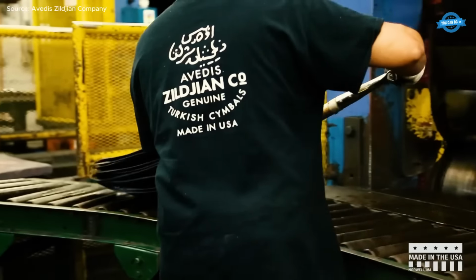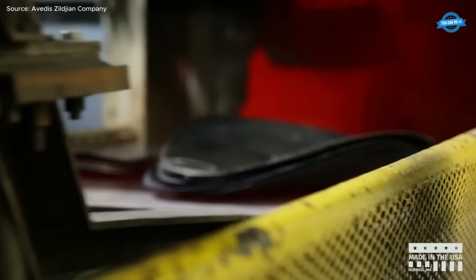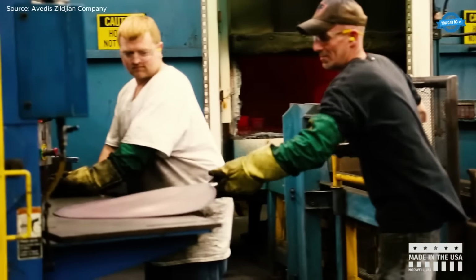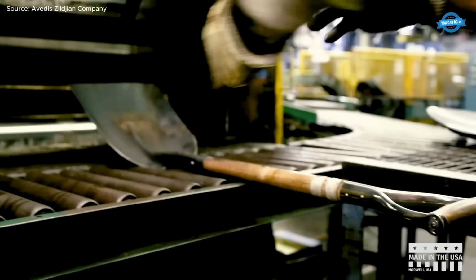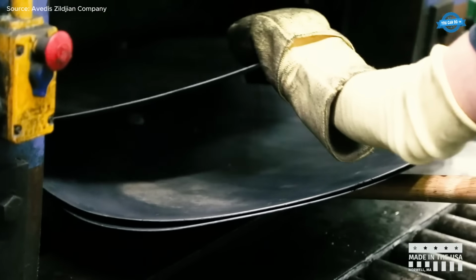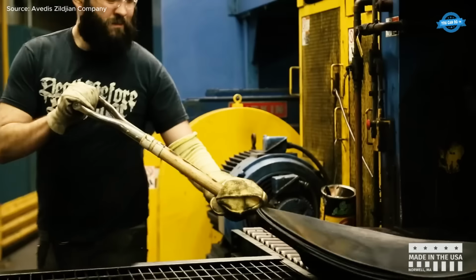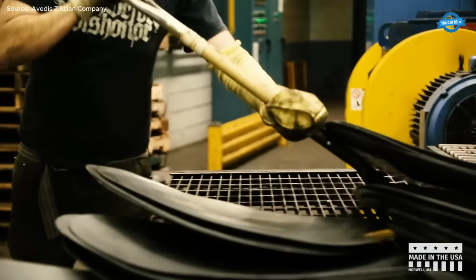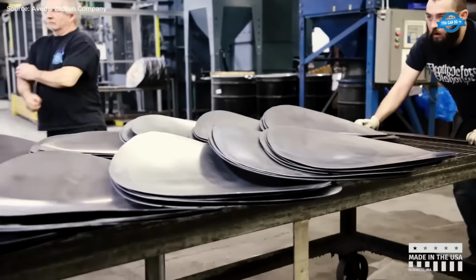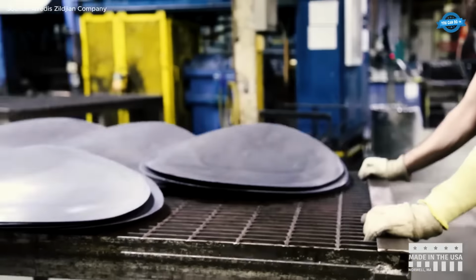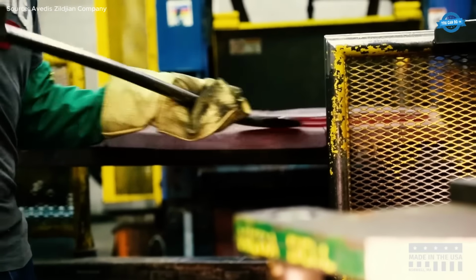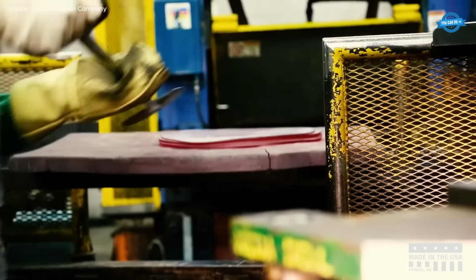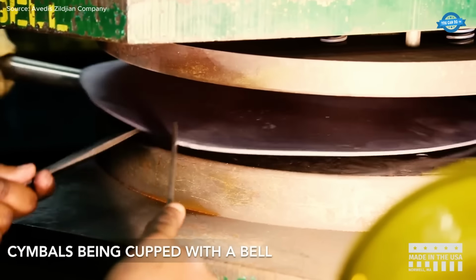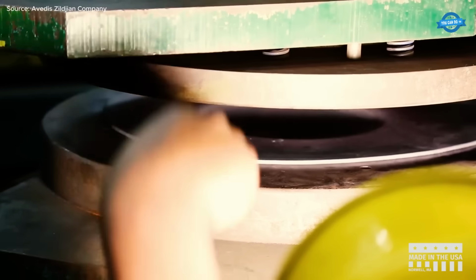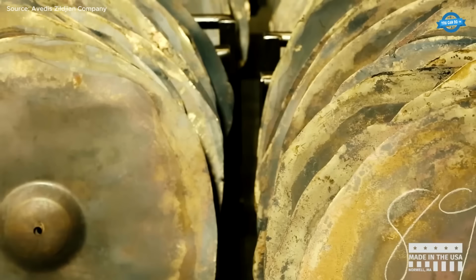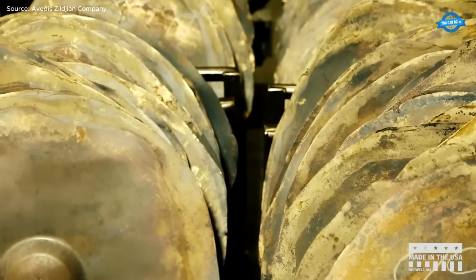After cooling, each casting is weighed, sorted, and transferred to high-temperature furnaces operating at approximately 1,400 degrees Fahrenheit. Heating prepares the alloy for mechanical deformation during the rolling stage. Once removed from the furnace, the hot bronze blank is passed through heavy rolling mills that gradually flatten the material into thin discs. This cycle of reheating and rolling is repeated 5 to 6 times, refining the internal grain structure while achieving the necessary thickness and flexibility for further forming.